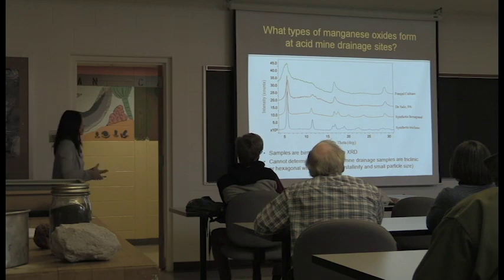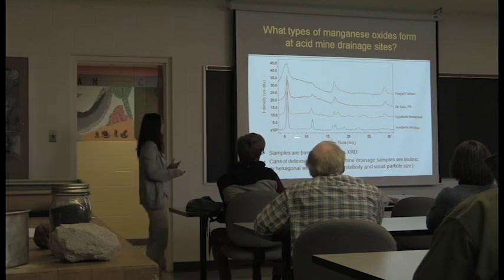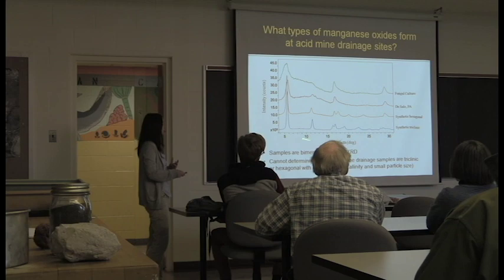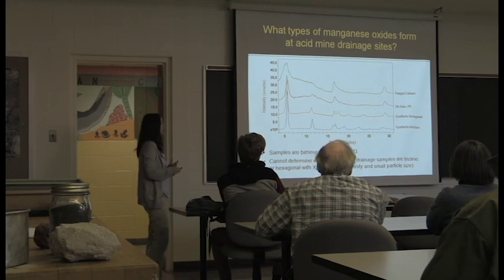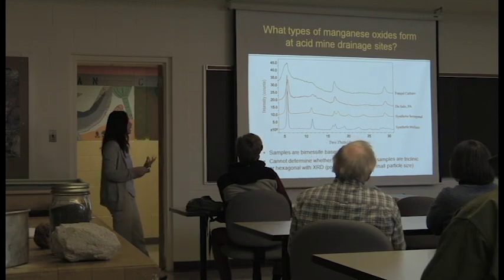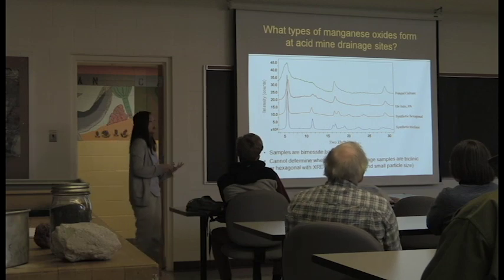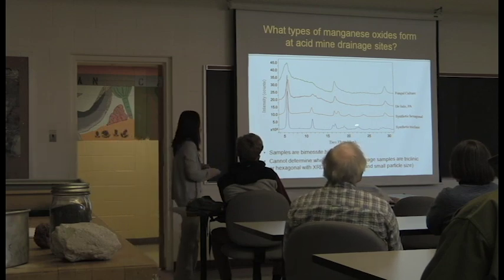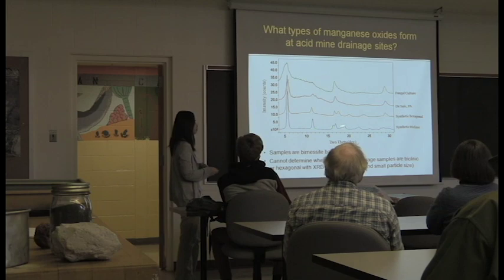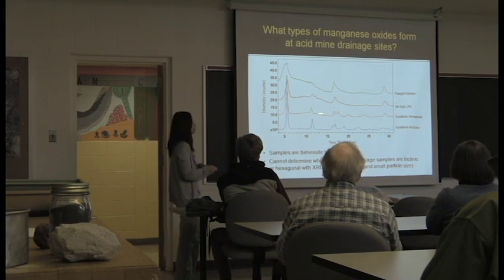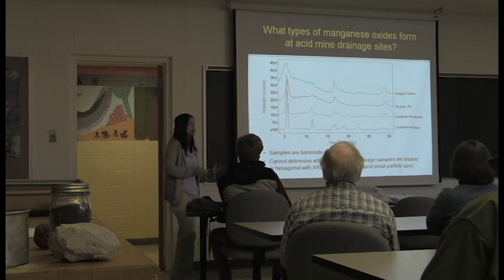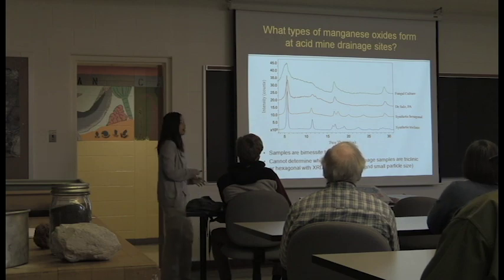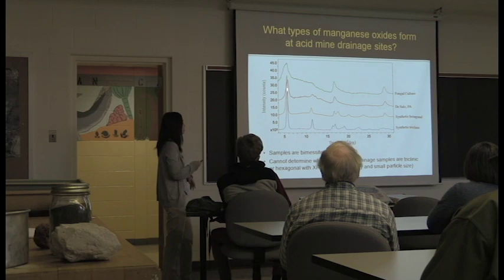This is what an X-ray diffraction pattern looks like. On the bottom you have 2 theta, which is that angle I was just telling you about. And then on the y-axis you have intensity, which is the intensity of the counts of the X-rays after they've been diffracted. This is what the diffraction pattern looks like for a synthetic triclinic birnessite. And this is what it looks like for a synthetic hexagonal birnessite. And these are, again, our very ideal laboratory materials. And the defining peak for birnessite is this peak right here around 5 to 6 degrees 2 theta.